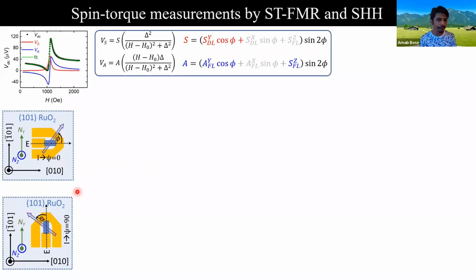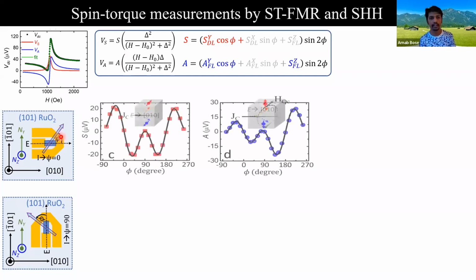First, let me discuss a couple of examples where we run current along the 0, 1, 0 direction, which I refer to as psi equal to 0. And then I discuss when we run current along psi equal to 90 along this direction. Just to remind you, here we are doing ST-FMR, meaning we run RF current and measure DC voltage by sweeping the external magnetic field at an angle phi. So here we get this ST-FMR voltage spectrum that is fitted to symmetric and antisymmetric Lorentzians. And now for a given crystallographic direction, we do the measurement for different values of phi to get the angular dependence of the symmetric and antisymmetric components.